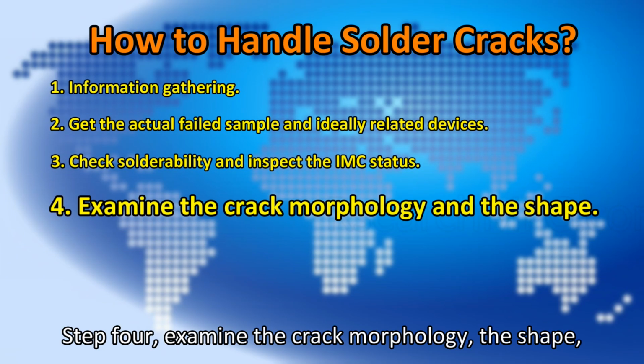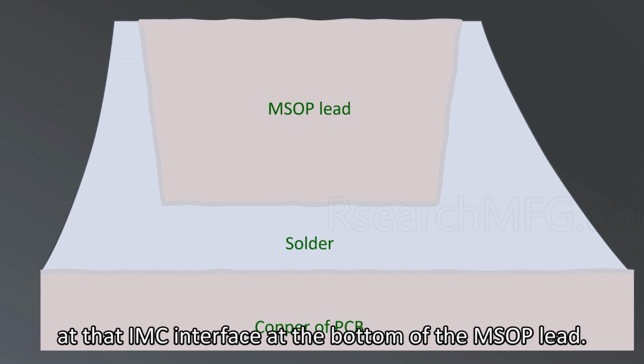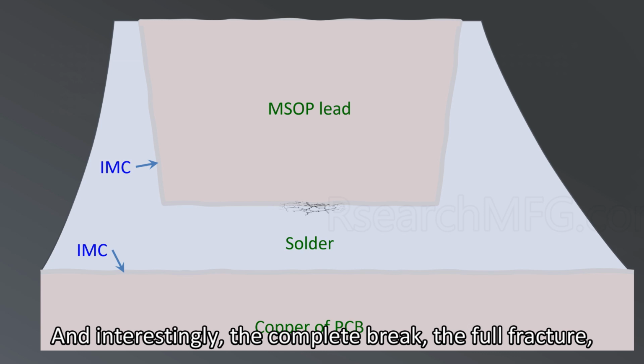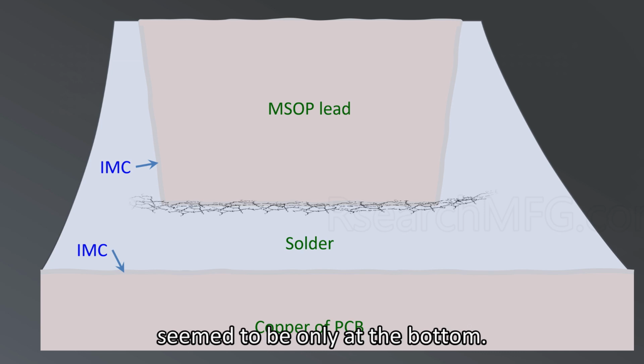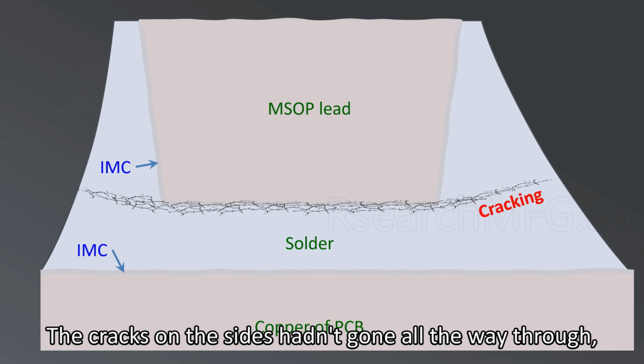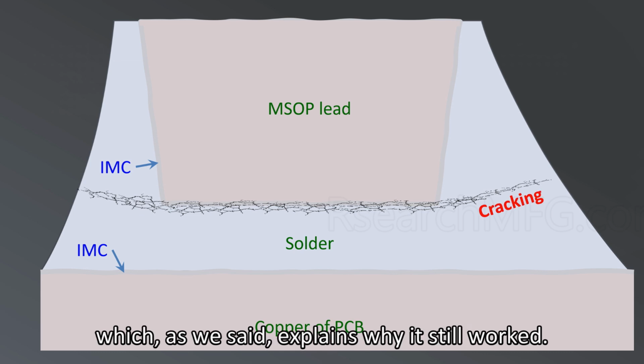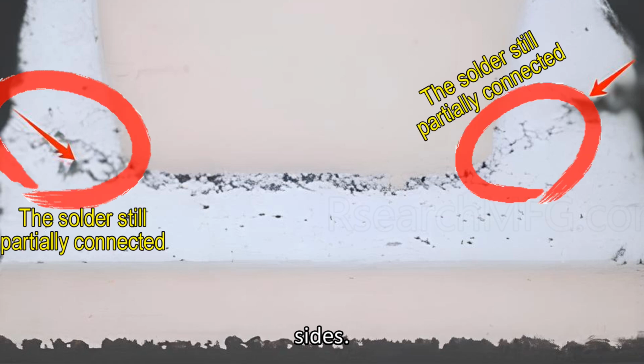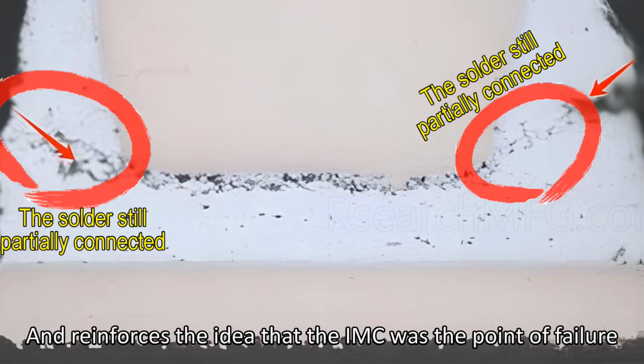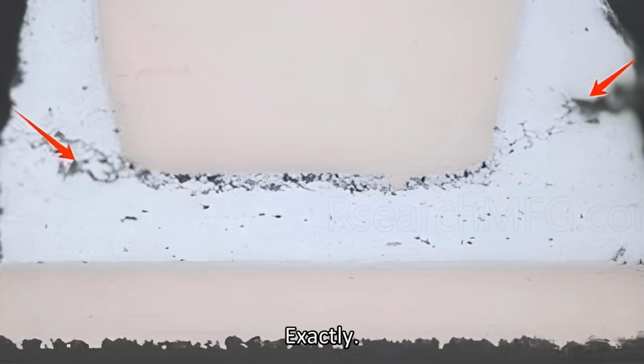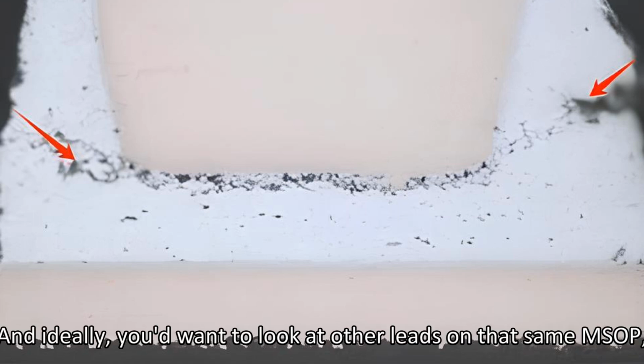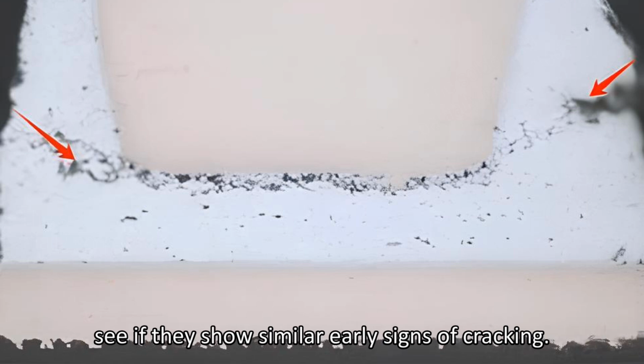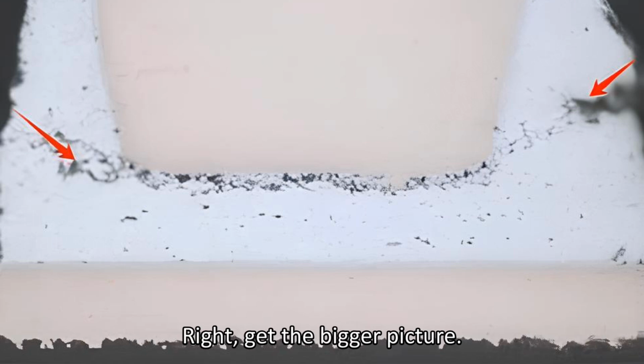Step 4, examine the crack morphology, the shape, the path it took. What did the photo suggest? It looked like the crack probably started right at that IMC interface at the bottom of the MSOP lead. And interestingly, the complete break, the full fracture, seemed to be only at the bottom. The cracks on the sides hadn't gone all the way through, which, as we said, explains why it still worked. Current could still sneak through the partly cracked sides. Makes perfect sense. Yeah. And reinforces the idea that the IMC was the point of failure initiation. Exactly. And ideally, you'd want to look at other leads on that same MSOP. See if they show similar early signs of cracking. Is it just one pin or systemic? Right, get the bigger picture.